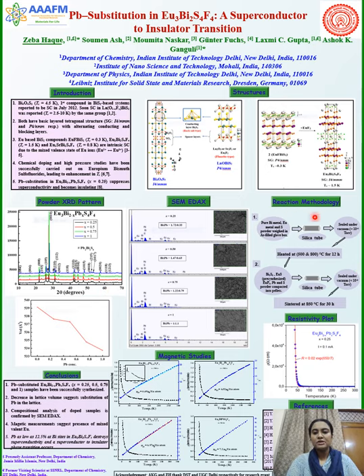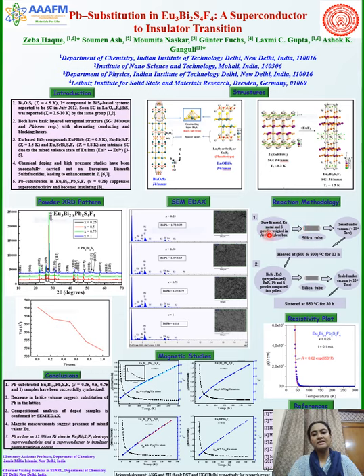The reaction methodology used was the solid state sealed tube quartz method. In the first step, we synthesized the precursors bismuth sulfide and europium sulfide. In the second step, we mixed these precursors with the remaining reactants: europium fluoride, lead powder, and bismuth powder.